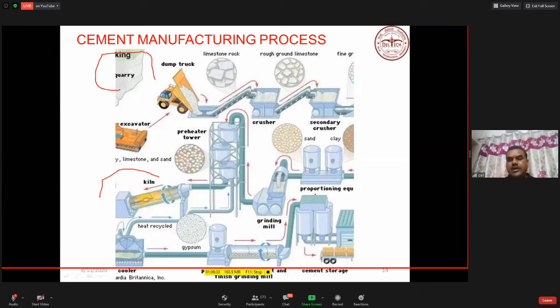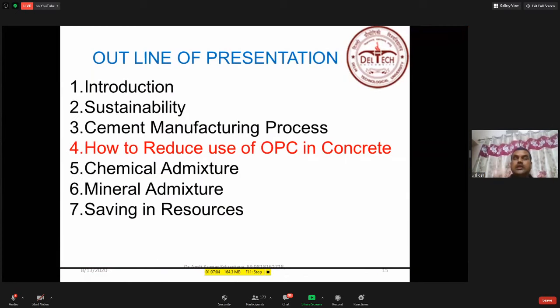Or if it is a slag cement or fly ash cement, then here you have to use the concept of mixing this material with the fly ash or slag. So now you see, whatever cement we are manufacturing, up to this point, it is ordinary Portland cement only. The last point where we distinguish is whether it is OPC, PPC or slag or different types of cements. Now this elaborate process causes emissions of carbon dioxide gas at the tune of about 1 kg per 1 kg of cement.